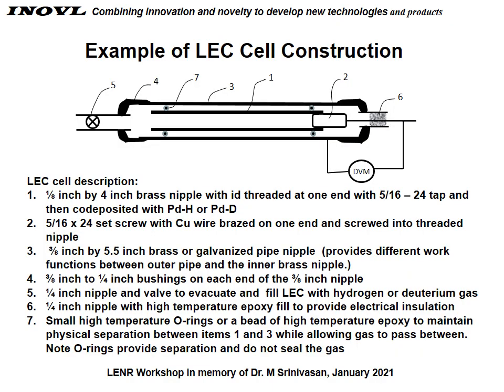This slide shows a cutaway view of a LEC. As you can see, it's pretty simple. In fact, virtually everything can be purchased at your local hardware store, starting with an 1/8 inch by 4 inch brass nipple, which is threaded at one end with a 5/16-24 tap, and then co-deposited with PdH or PdD. This becomes the working electrode.